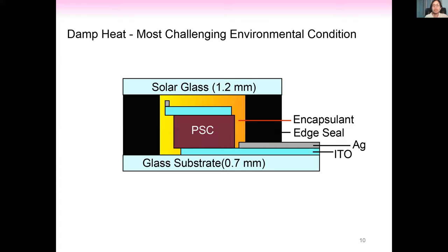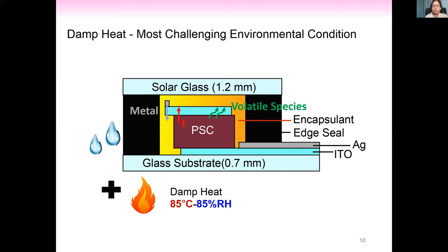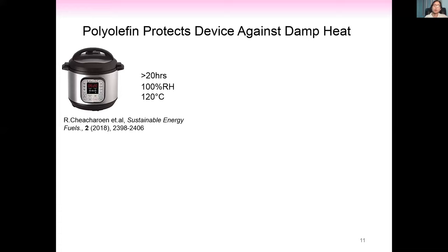The complete simple package design that passed all three IEC tests includes: a compliant encapsulant for mechanical robustness during temperature cycling; a chemically inert encapsulant — polyolefin; glass and edge seal to protect against moisture; and on-substrate electrical feed-throughs instead of solar ribbon to minimize moisture ingress through the package. Additionally, no vertical overlap between metal and perovskite is needed to prevent metal-induced perovskite degradation.